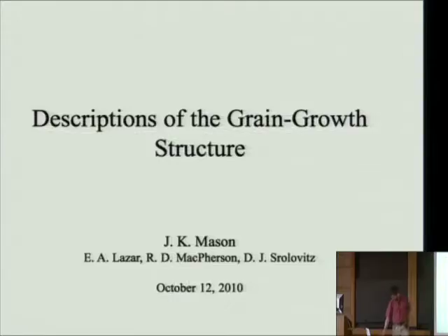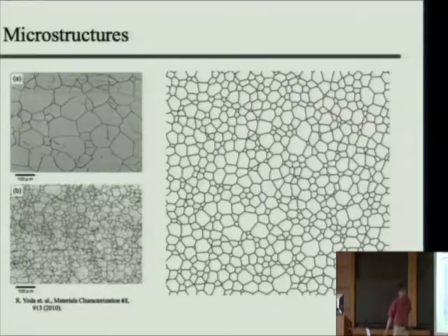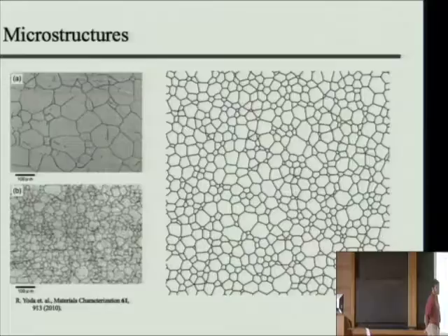How were they treated? Was the first one treated, cooled slower or something? Well, probably what was going on is this one was just annealed. All the boundaries have some excess energy associated with them, and if you bring a metal up to about 2/3 of its melting temperature, the kinetics are fast enough that this happens on reasonable time scales, like a couple hours.